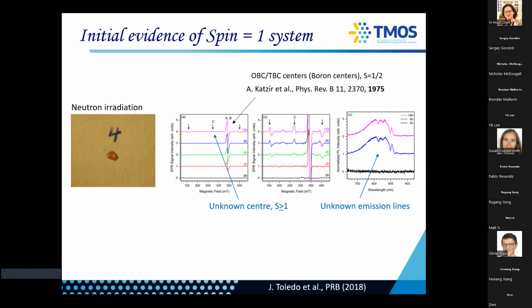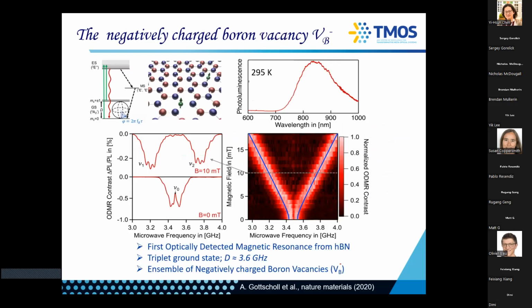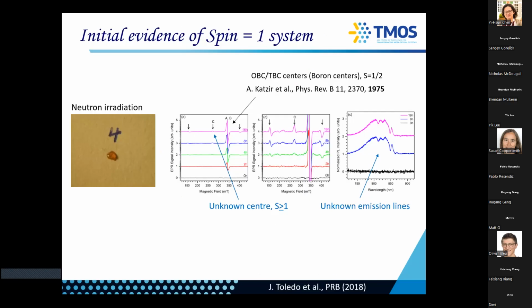Now, all these peaks are artifacts of our spectrometer. This is how you do bad science, and it cascades down the literature. We didn't realize back then that this is actually an effect of our mirror coating, because we never were working in this 850 nanometer range. So the emission looks like that. It's just smooth. Okay, we obviously corrected since then, but the emission should just be smooth.